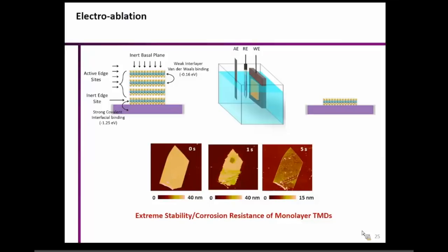Now, generally, these 2D materials are very inert in the basal plane. So nothing actually happens from the basal plane direction. It is chemically very inert. But the edge sites are the ones which are defective, and that's where all the chemicals start to attack this 2D material. Now, you can see in this temporal evolution of the AFM images that at the beginning I have a flake, and as the process proceeds, I am etching this material from the side. So it's from side to center etching, but then miraculously this last layer survives.